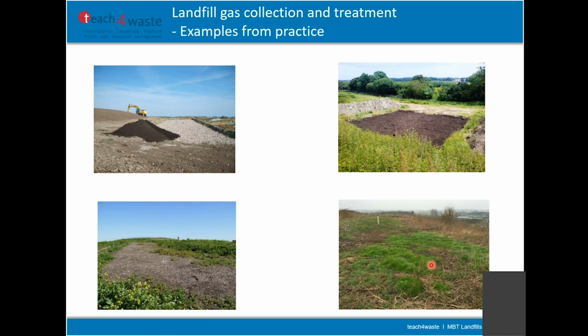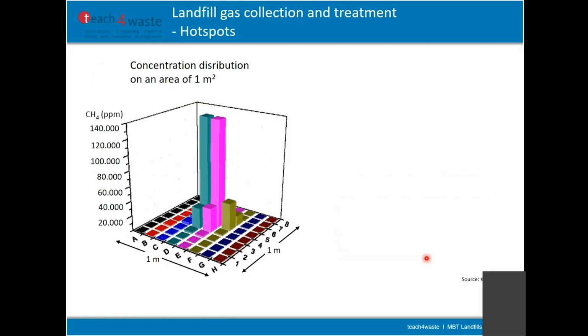But what might happen, and this nearly always happens, is that we get some hotspots. So you have to monitor the system. Every year you make some measurements on the surface, and what you might see after a while are these hotspots. This is a quite small area, 1 square meter, 1 by 1 meter, and you see a lot of measurements have been made in this area. And in very small areas, you have very, very high concentrations of methane. Small parts only with high concentration; in the remaining area, the methane oxidation is working quite well.